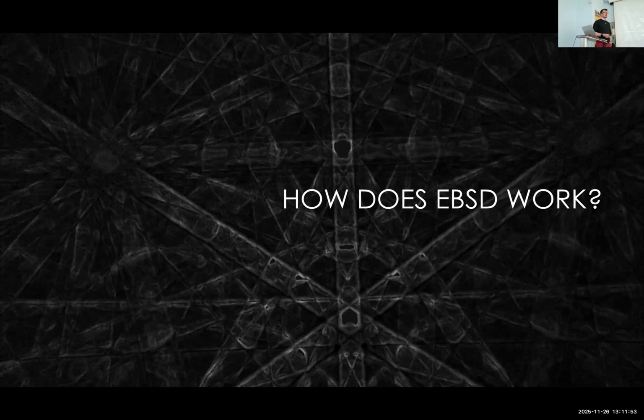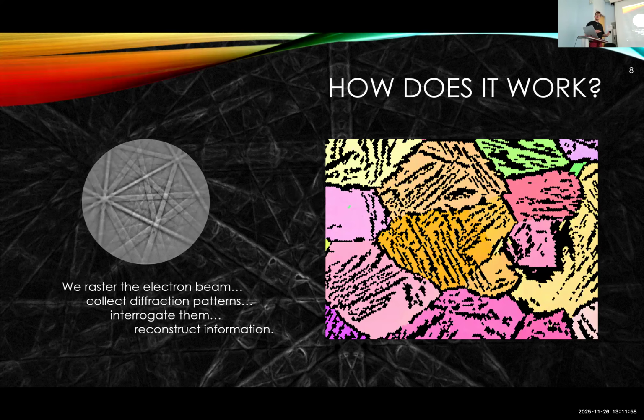But I wanted to give a bit of the sort of theory behind how the technique works. Fundamentally, we're going to use the scanning electron microscope to move the electron beam across the surface of our sample. And we're going to synchronize the collection of a two-dimensional diffraction pattern at every single point within this map. We're then going to use online, typically, algorithms to identify the crystal structure. This is a body-centered cubic pattern, and the crystal orientation. And that's the orientation of the cube with respect to a reference crystal direction.